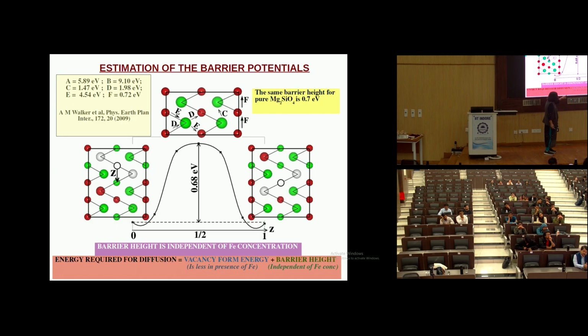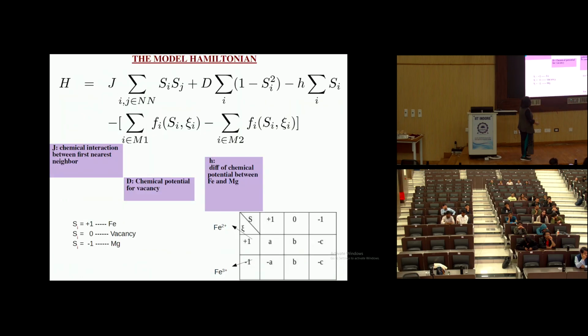So the energy required for vacancy diffusion is actually a contribution from two. One is the vacancy formation energy, which is highly affected by the presence of iron, and the barrier height, which is much less affected by the presence of iron. And now we complicated the Ising-like Hamiltonian that I have shown you before. Now it is not spin half. If it was spin half, I would have plus half and minus half. Now I have three species.